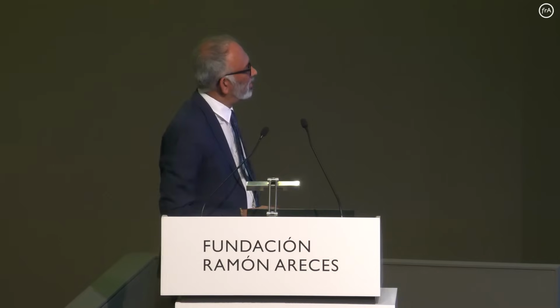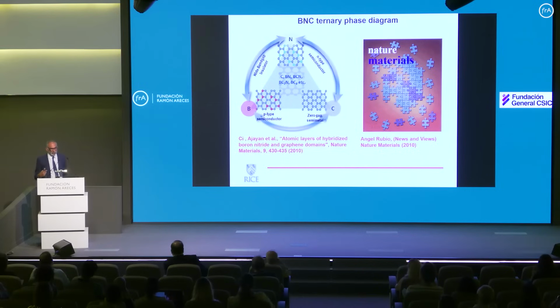And this is one system where this type of structure is possible: boron, nitrogen, carbon. Carbon we already saw, graphene, an atomically thin layered system. Boron nitride is another material which looks exactly like graphite, exactly like graphene. One layer of boron nitride has the same structure as graphene, but because it's made of boron and nitrogen, they form a very strong ionic material which becomes electrically insulating.